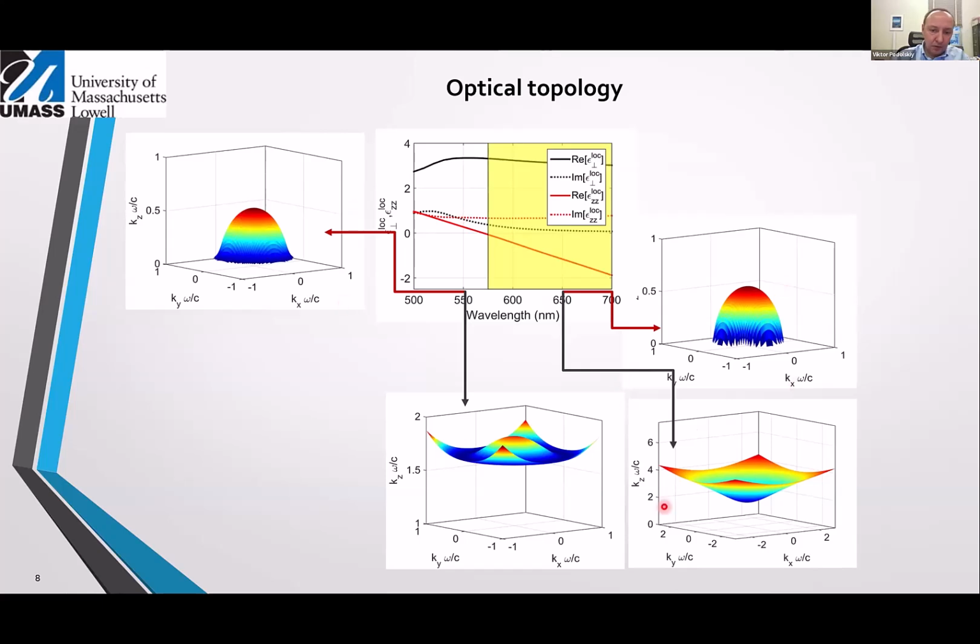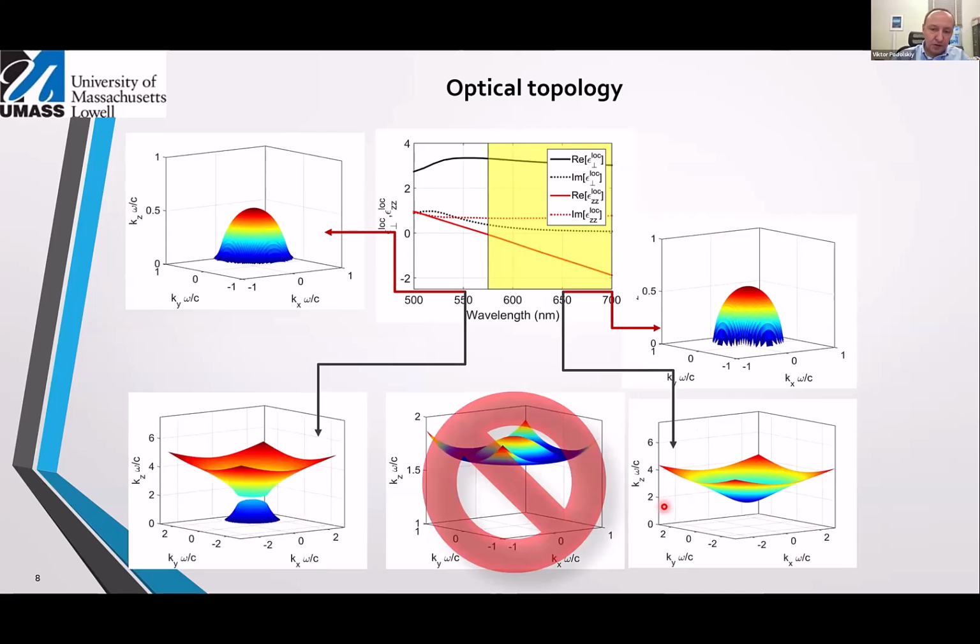And so these are the dispersions of the modes that one would expect to see. And these are the dispersions of the modes that come from the finite element solutions of Maxwell equations. And what you can see is that the elliptical modes or the circular modes that are not affected by anisotropy, they are perfectly modeled by effective medium response. The high wavelength dynamics, again, is hyperbolic and perfectly modeled by effective medium response. But this low wavelength regime is interesting, and there we numerically can identify two different modes.